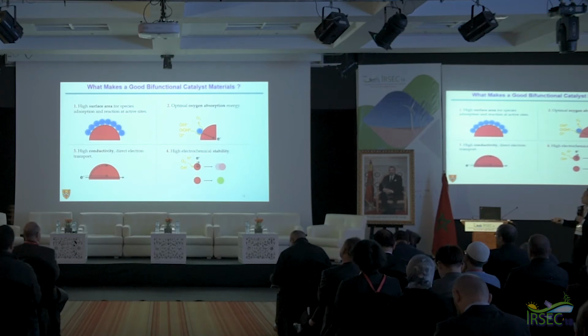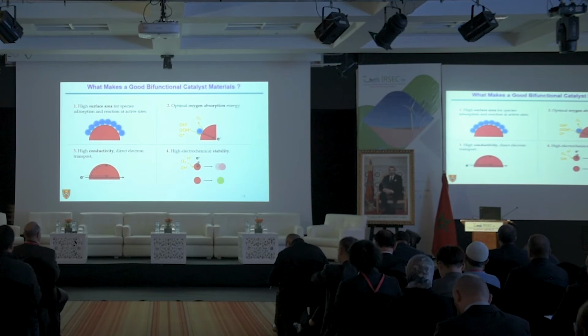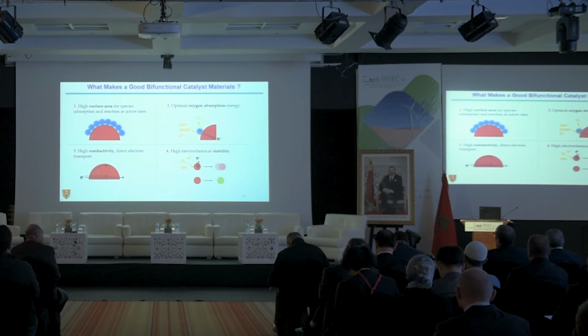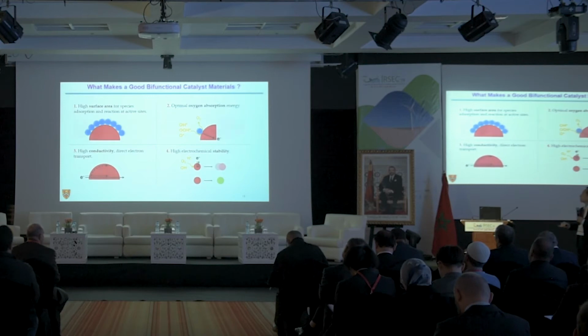And then number 4 is stability. Because for all these reactions, during charge and discharge, it's from low voltage to high voltage, which means corrosion happens very fast. If your catalyst is not stable, then the battery lifetime will be short, right? So we have to meet these 4 requirements in order to design a good bifunctional catalyst.